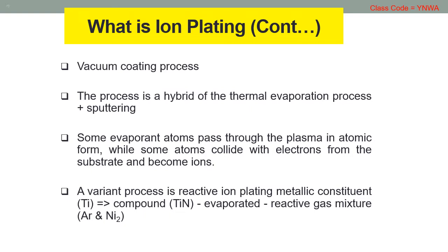Ion plating is a vacuum coating process in which a portion of the coating species impinges on the substrate in ionic form. The process is a hybrid of the thermal evaporation process and sputtering, with the evaporation rate being maintained at a higher rate than the atoms that can be sputtered from the substrate. Some evaporant atoms pass through the plasma in atomic form, while some atoms collide with electrons from the substrate and become ions. They impinge on the substrate in ionic form, pick up electrons, and return to the atomic state, forming